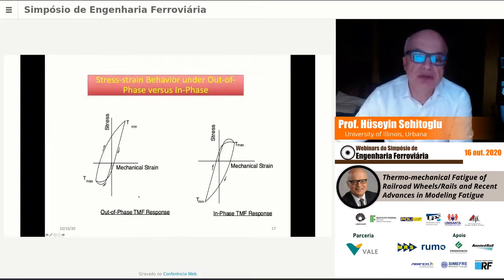Typical stress strain behavior is also different for out of phase versus in phase. In the out of phase, you're heating the sample and you're going into compression, and that's the maximum temperature. And then you cool, and then you are in tension. So in strain wise, your maximum strain and minimum temperature coincide here, and here the maximum temperature and the minimum strain coincide. So this is the out of phase case.